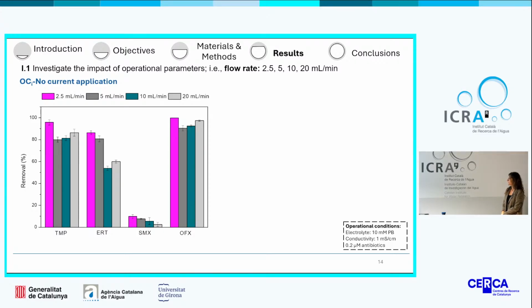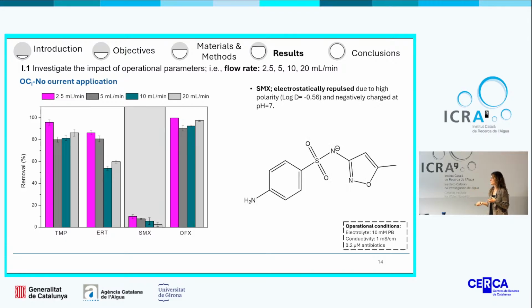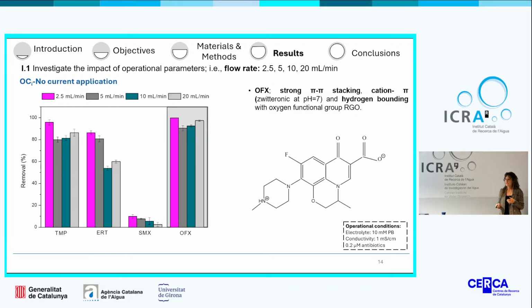According to the results, and starting from the flow rate during the open circuit conditions, as we can see in this graph is represented the removal of the 4 studied antibiotics. There are significant differences between the behavior, as for example, in case of sulfamethoxazole, which is poorly absorbed onto the sponge. This is probably a consequence of the electrostatic repulsion between the negatively charged reduced graphene oxide and the negatively charged sulfamethoxazole at neutral pH.